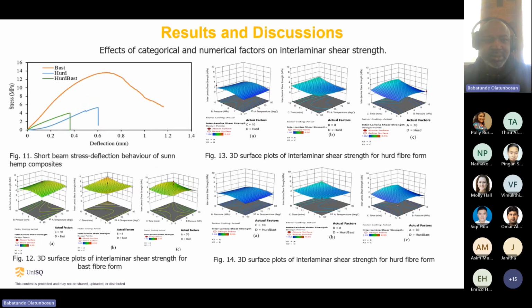Now, this slide talks about the effect of categorical and numerical factors on the shear strength of the composite produced using different forms of sun hemp fiber and a bio-epoxy. Figure 11 is the short beam stress deflection behavior of sun hemp. The interlaminar shear is highest for bast as well. Bast is the highest among them. You can see the deflection is around 1.2, while the hurd has the lowest, which is around 4 megapascal.